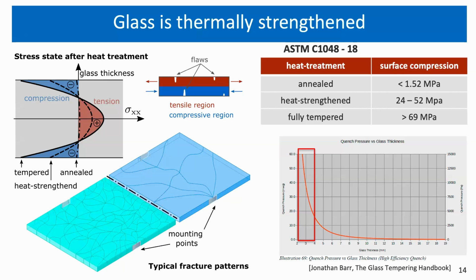And one issue that we came across is the thermal strengthening of the glass, especially since it's so thin. Most of the standards only specify the heat treatment for thicknesses above 3 millimeters. And then you can usually differentiate between tempered glass and heat strengthened glass. Tempered glass usually fractures into a lot of small pieces, versus heat strengthened glass, which has a fracture characteristic similar to annealed glass.